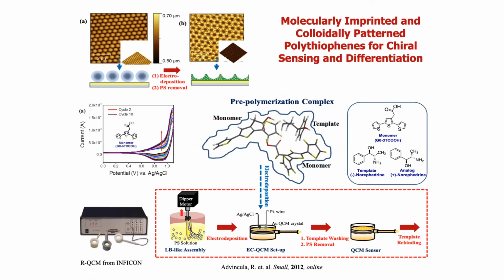Now, another way that we utilize these patterns is to demonstrate molecular imprinting. Molecular imprinting is a method of producing an enzyme-like activity where the lock and key mechanism was demonstrated by using a template molecule, and in our case, using an electropolymerizable monomer complex of this monomer and analyte, and then electrodepositing them on a quartz crystal microbalance surface. After depositing, we would remove the template and we should be left with an array structure similar to before. So the AFM here again confirmed the formation of this patterned array, hopefully with the cavities of the original template molecule embedded on those arrays.